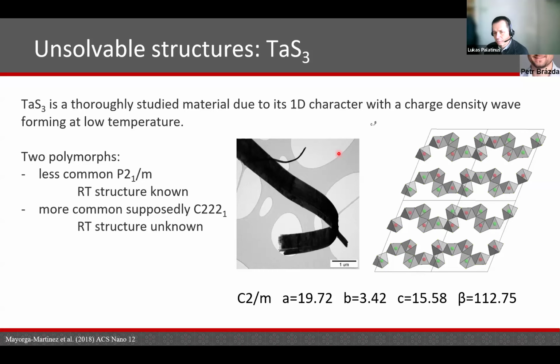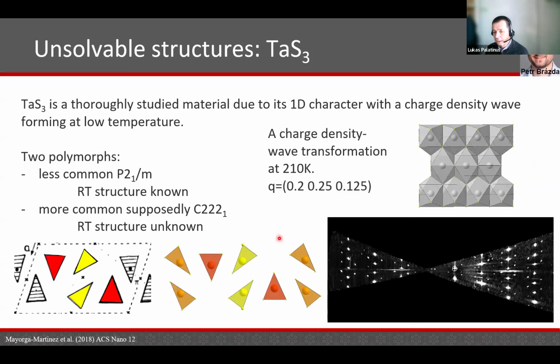With electron diffraction, this was a matter of one day to solve the structure, because even though the crystal is very bent, it's possible to collect data from maybe this part here, or even from some small part of the crystal like this. It was possible to solve the structure relatively easily, and so finish really decades of uncertainty about the crystal structure of this material. And even better, at low temperature, this material is modulated. So it has a charge density wave structure with a modulation vector. You can see the modulation here. These are the small spots next to the main reflections, and it was possible to determine even the modulated structure with electron diffraction.